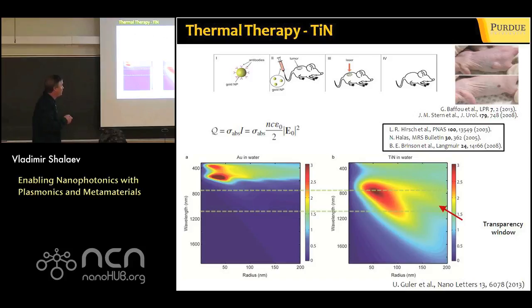What they use is gold nanoparticles. But if you take conventional colloidal gold particles, the plasmon resonance is outside of the biological transparency window. For gold, it's around 540 nanometers. So it's not really in the biological transparency window. What they do instead of using colloidal particles is use nanoshells. Basically, it's a dielectric core coated with a gold shell. That shifts the resonance because it's not a sphere anymore, and that shifts the resonance to this biological transparency window.